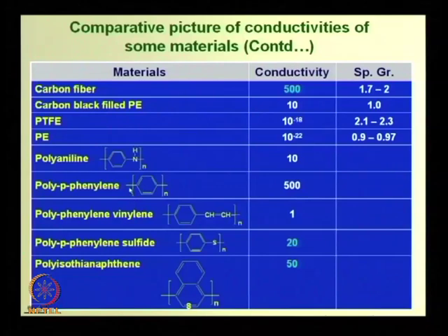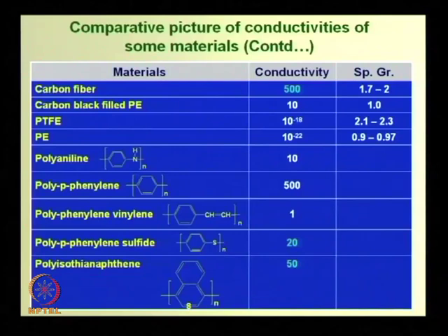Okay. Then you take that emeraldine salt, put in some base, means ammonia solution. So, it will be converted to base form, means HCl is removed from there. Now, that base form is soluble in organic solvent, but base form is not conducting.